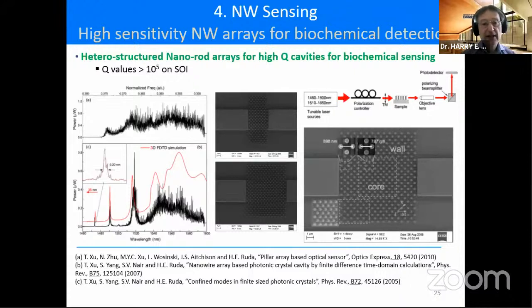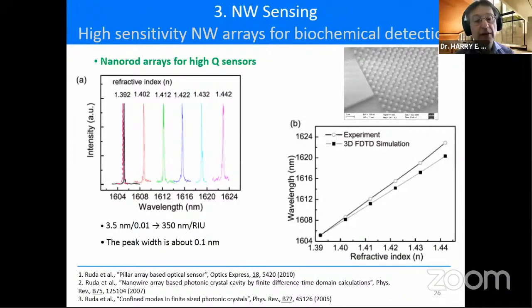But I'll cut to the chase: these structures enable you to have very high Q modes with Q values in excess of 10 to the 5. And so what that means is when we look here in this next slide on the left, you'll see that the peaks are very, very sharp, very narrow. So that means that any change from an absorbent on that peak is going to be seen. And to show you the effect of a small change in refractive index, you have different refractive index media changing the contrast in the cavity, and you can see very dramatic changes of the order of 350 nanometers per refractive index unit. So these are very sensitive sensors that can detect, therefore, very small concentrations of analytes.